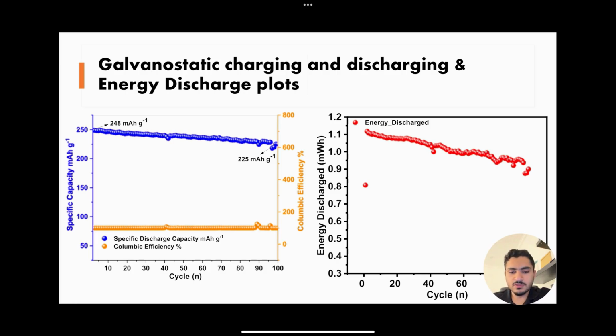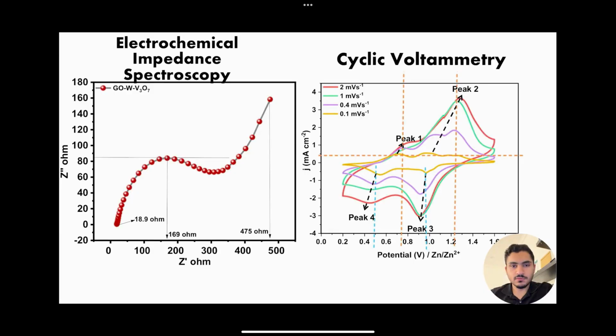On the right, we have the energy discharge, where we started with about 1.2, and after 100 cycles, it dropped to about 0.85. Then we have the electrochemical impedance spectroscopy and cyclic voltammetry. For electrochemical impedance spectroscopy, we can extract 3 important pieces of information. The first is the solution resistance, which gives us about 18.9 ohms. Second is the charge transfer resistance, which gives about 169 ohms. And lastly is the Warburg impedance, which gives about 475 ohms.